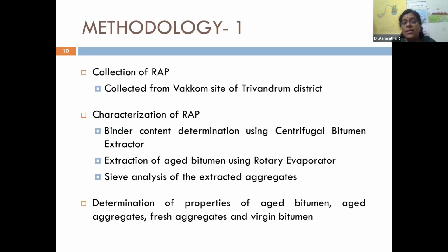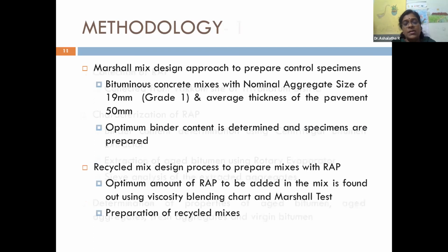And also we determined the properties of the aged bitumen, aged aggregates, and the fresh aggregates, because we need some fresh aggregates too, as well as the virgin bitumen. So all those properties were tested, and the Marshall mix design approach to prepare control specimens was adopted, and bituminous concrete mix with nominal aggregate size of 19 mm, that's grade 1, and average pavement thickness of 50 mm, was adopted. And we determined the binder content, and the specimens were prepared. Based on that, we first found out the optimum bitumen content, and we prepared the specimens, and then we conducted the various tests on it.